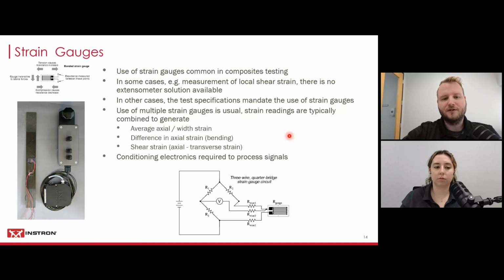You can do the differences in the axial strain to determine the bending that is going on during your testing, and that is a very important part, especially for compression testing, because you don't want any kind of bending or buckling going on. And then you can also use multiple strain gauges to determine shear strains, for example.